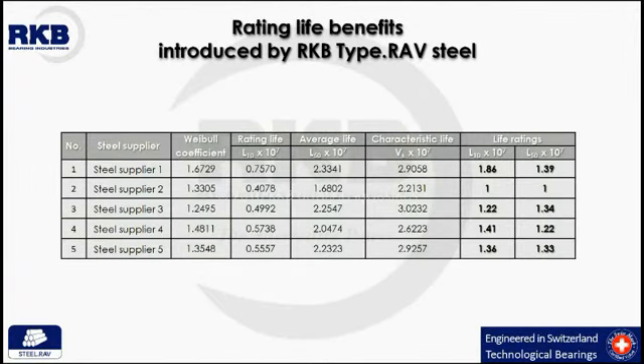In order to verify the quality of our bearing steel, we performed a rolling contact fatigue life test. We selected 5 leading steel suppliers, and on one of them we imposed to respect our RKB Type.RAV bearing steel protocol for premium reliability in critical severe applications, equivalent to grade 6 and grade 7.